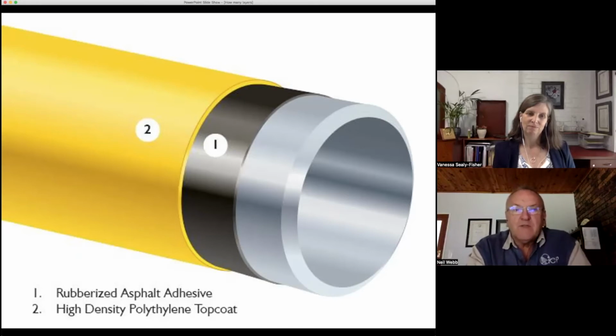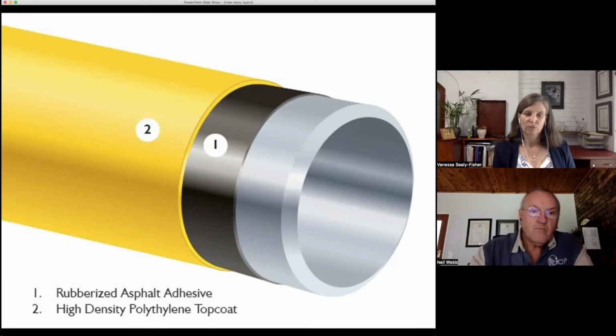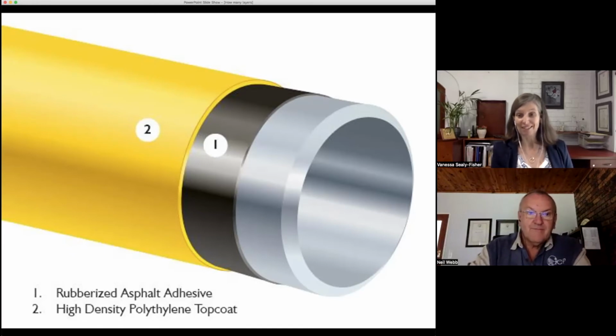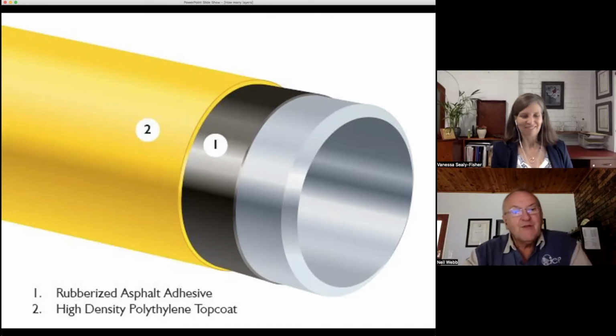bitumen-based adhesive, a mixture of bitumen and polymers, very much like we use in many other products for the pipeline industry. And it is used between the steel and the polyethylene because it is one of the few things that does provide you with some adhesion, some chemical adhesion, and also it provides you with good chemical resistance or corrosion resistance on the layer underneath the polyethylene up against the steel itself. So effectively, you've described something now that is two layers, and I suppose we could term it two-layer polyethylene. Well, you're absolutely spot on the money there, because you will find two-layer polyethylene described in the literature and in the standards as one of the material systems that is available for pipeline coatings.